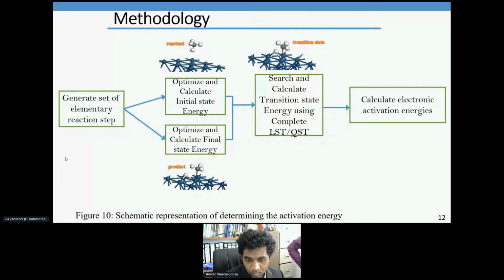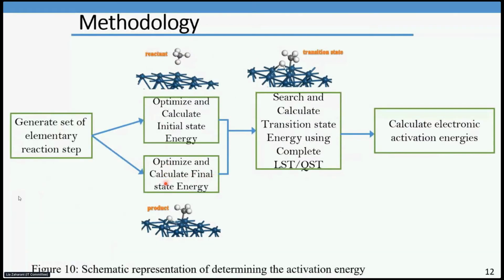This figure shows the schematic representation of determining the activation energy, in which we generate the set of elementary reaction steps, then optimize and calculate the initial state energy. Here we have the methane adsorbed on the surface, and optimize and calculate the final state energy. Then we have the CH3 plus hydrogen. Now we search and calculate the transition state using the LST/QST method. After that, we will calculate the activation energy.